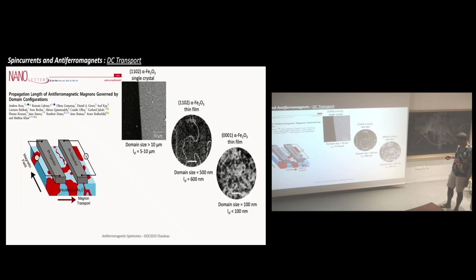And then to show that you actually needed a very nice control material, the same group reproduced that, but not this time on thin layer. I think that was thin layer, I need to check again. But the nice thing, they could check if there is a domain pattern, if there are different domains. And you could see that the spin diffusion length, the characteristic length on which you can convey the spin information, was highly dependent on the size of the domain.